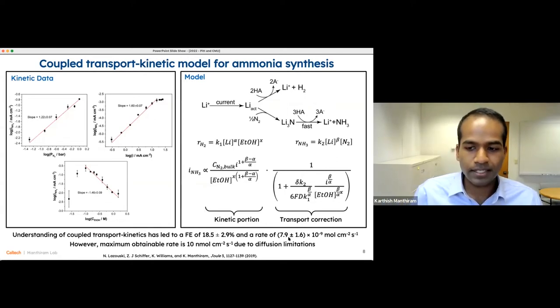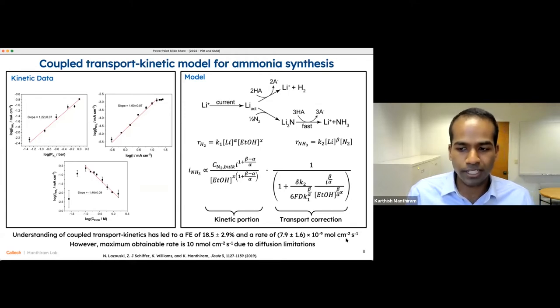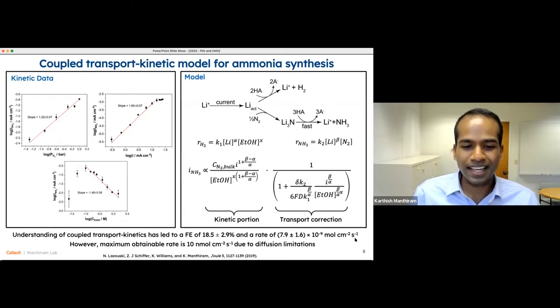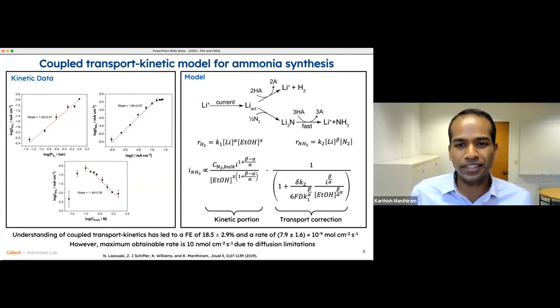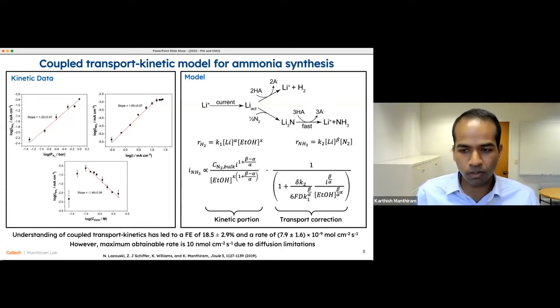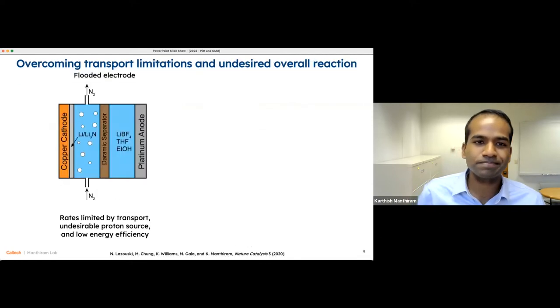The rate here is about 10 nanomoles per centimeter squared per second. And the issue here is that that is just about at the transport limited rate. That's the highest rate that we can achieve. And even if we were to make better interfacial catalysts and processes for somehow fixing nitrogen faster, that would be entirely masked by transport in this system. So it is really important that we find a way of overcoming that transport limitation to break that limit of 10 nanomoles per centimeter squared per second. And that's a number that we'll come back to shortly.